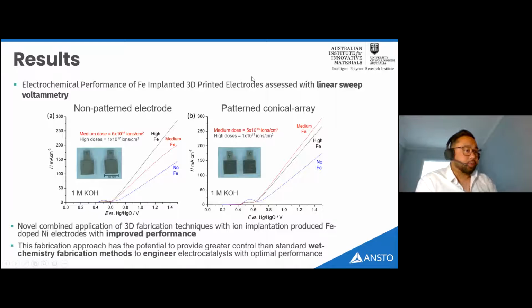So this slide shows preliminary results of linear sweep voltammetry performed on these electrodes, on both a non-patterned electrode on the left and a patterned electrode on the right, for no implantation, for medium dose and a high dose implantation. And what you can hopefully see is that the implanted iron improves the catalytic current for both non-patterned and patterned electrodes and for both medium and high dose.